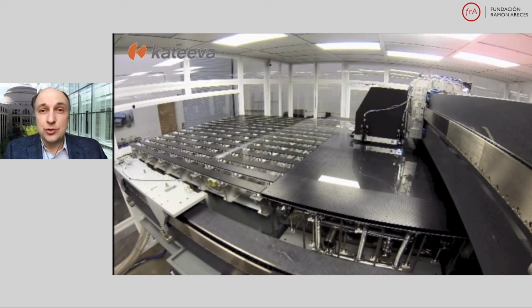You have chosen to use a substrate that is much bigger than today's silicon wafers, 2 by 2 meters in size to be exact. We are putting down films with an accuracy of 10 nanometers rather than the microns that some of the silicon devices require. And indeed, the yield, the functional operation of every device we make, needs to be exactly the same, because your eye can pick out 1 out of 4 million bad pixels on your TV screen. Your yields need to exceed 99%. It needs to be 99.9 and keep counting.